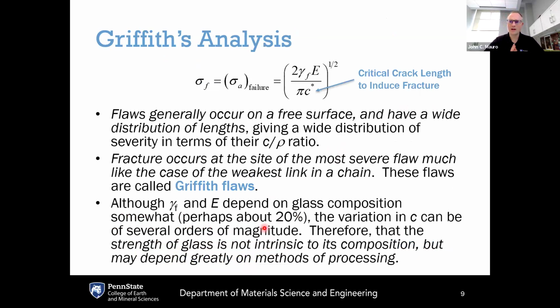Now, the more common way of thinking about the reduction of the strength of brittle materials is due to Griffith, because Griffith is the one who introduced the presence of surface flaws. And in fact, surfaces of glasses or other brittle materials are what gets exposed to the environment. This is where we touch the glass. This is where it tends to undergo the greatest amount of damage. And so with Griffith's analysis, he based his analysis on basically the length of the crack, as well as the sharpness of the crack tip.